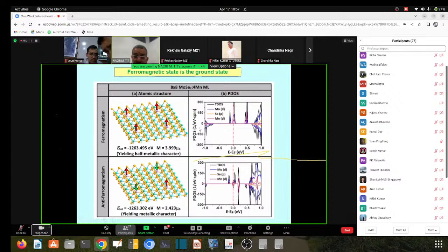Anyway, we also tested this to show the referees. Probably we did it before the referees, because our first submission is under review. We submitted this one, I think, to Materials. So we tested the ferromagnetic state and the anti-ferromagnetic state, and we have shown that the total energy favors the ferromagnetic state. And this is a sample of 8x8. This is our first sample that we went beyond 6x6 with VASP. So to test the 4x4 sample, like we did also in the case of defect or vacancy.